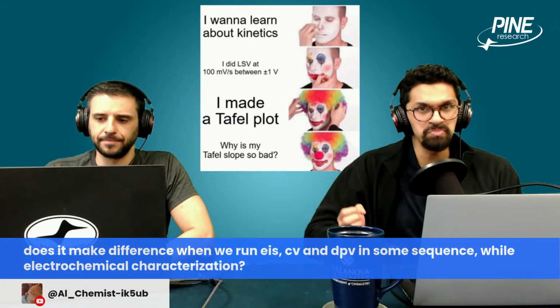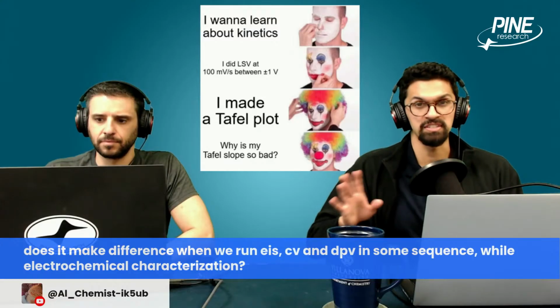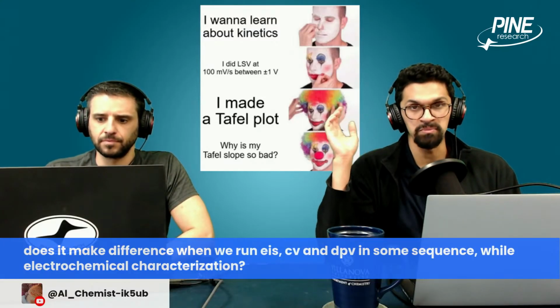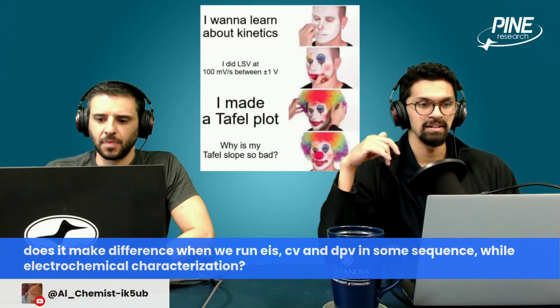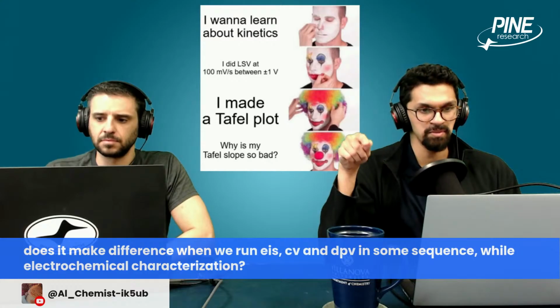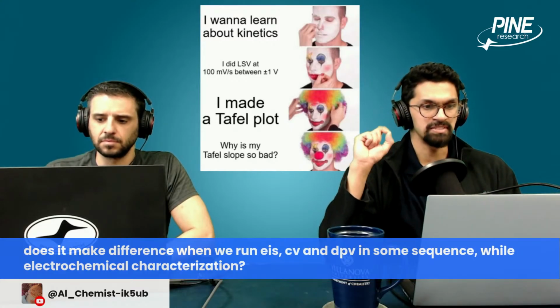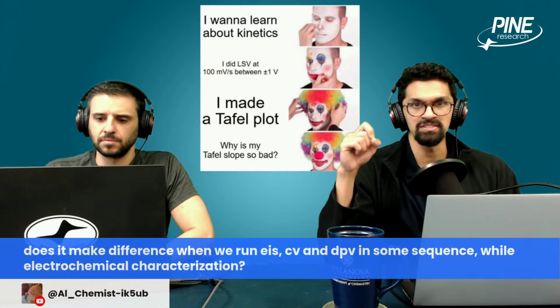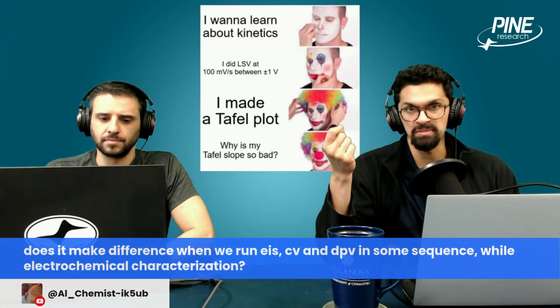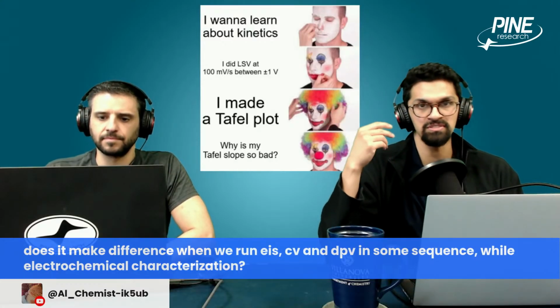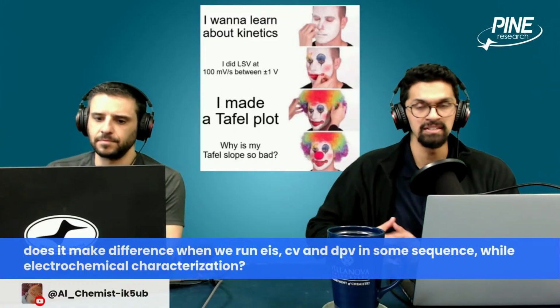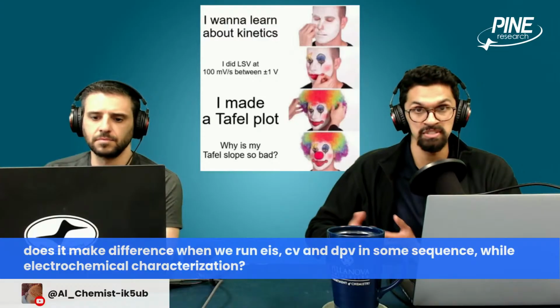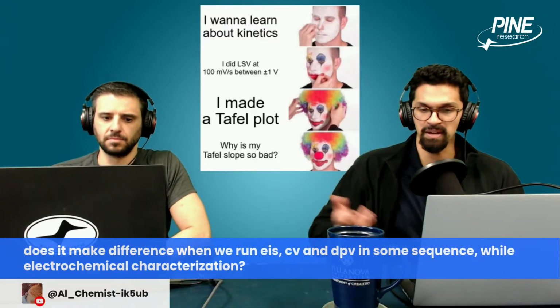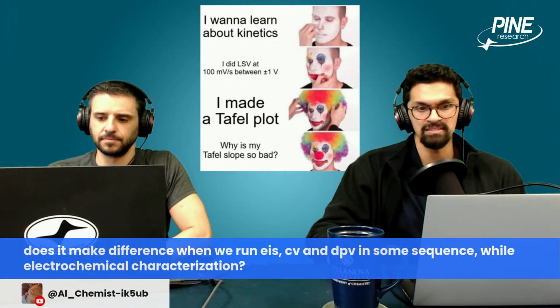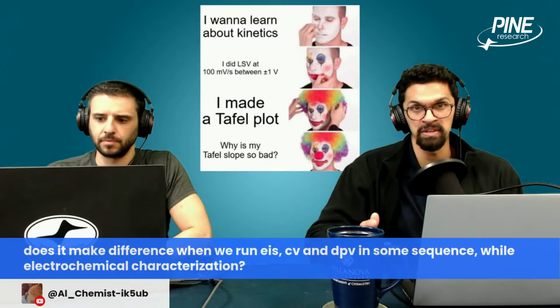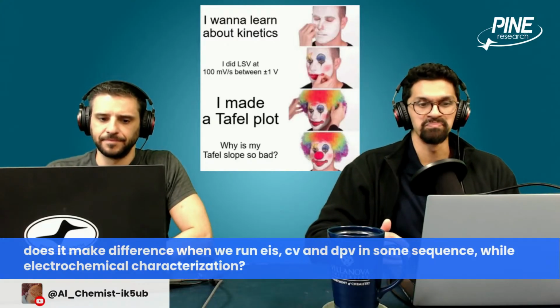So generally speaking, depending on the system, if the system is perfectly reversible and stuff like that, then it wouldn't matter. But it's rarely the case. Generally speaking, with EIS, I don't think it really matters so much because it doesn't perturb the system as much. But CV and DPV have a much higher chance of changing the system because they're much larger perturbations, and your EIS before and after DPV or CV may look very different because the technique changed the system in some way. So that's my take on the question. Hopefully that answers it. If you have further questions about what order you should do things in based on this, let us know.